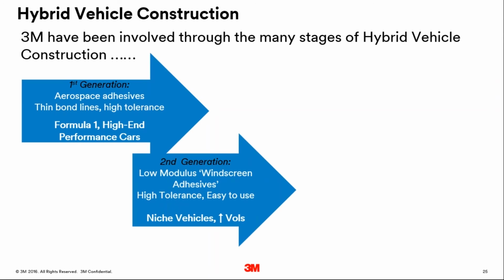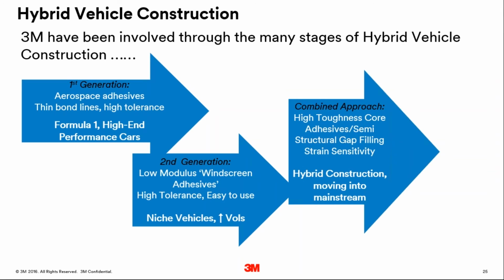But it does not get the best out of your high performance material in terms of stiffness and load transfer. Therefore, in recent years, we've moved over to a combined approach using high toughness core adhesives and then semi-structural gap filling adhesives in less demanding applications, all the time respecting the strain sensitivity of the high performance substrates such as composites. And this is moving hybrid construction into the mainstream. And we've seen a number of manufacturers recently incorporating some quite exotic materials into what you would call mainstream vehicles.